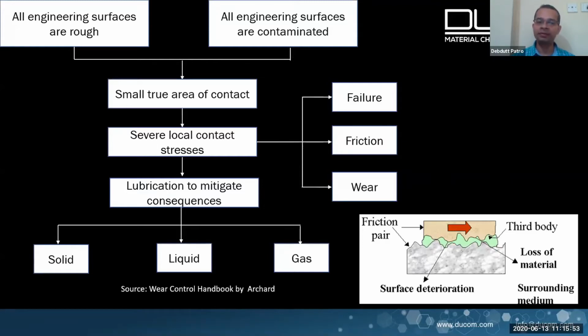And when these rough surfaces which have contamination rub against each other, they rub against asperities which are there on the surface. And when these small asperities contact each other, you get local stresses which are fairly high. And when these local stresses exceed some of the material properties which are very surface specific, you could get failure, which could be fatigue, but you could also have friction being generated when these surfaces or the asperities rub against each other. And when you exceed certain strength parameters of the material, you could have those asperities removed and get wear. So contacting surfaces rubbing against each other at asperities would eventually lead to these different modes of degradation, which is failure, friction, and wear. And one way in which we can mitigate is by adding some form of lubricant.